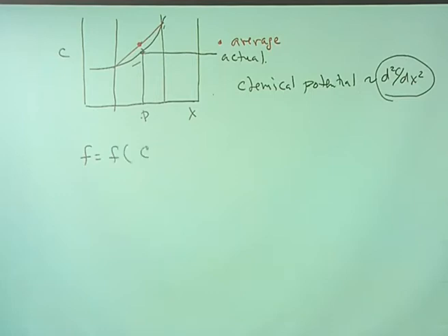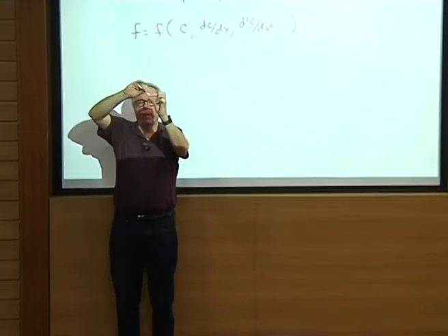can be a function of composition. This is what I just gave you before. F, I'm using F here because I've gone back to the Cahn-Hilliard Helmholtz free energy, but it really doesn't matter. It can be a function of, let's say, the gradient in the composition. It can be a function of the second derivative of the free energy, for example. And I want to make sure that everyone understands exactly what I mean by this: if I go to a point P and I give you the composition, you won't know the free energy until I also give you some information about the gradients.